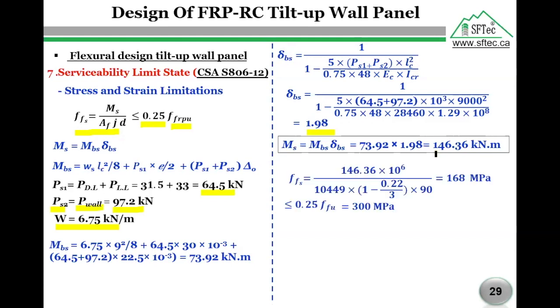Now we are going to calculate the maximum stress in the FRP bar under service load. The maximum stress equals 168. This should be less than or equal to 0.25 of the maximum limit of the tensile strength of the used bar. So this one is okay. Now we have the maximum stress in the used FRP bars under service load, and the elastic modulus is known for us. So we can calculate the maximum strain in the used FRP bars under service load. The maximum strain equals 0.0026.